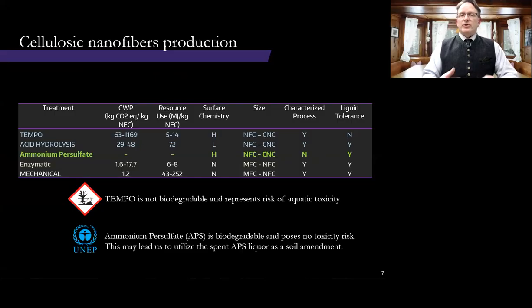With regards to the way we produce nanofibers, there are three methods for producing nanofibers: chemical, enzymatic, and through mechanical means. This table summarizes the environmental impact, the energy requirements, and then what that process is capable of developing in nanofibrillated cellulose. But to produce a nanofiber that helps solve our environmental problem, we really need to have an environmentally friendly method. And of all these methods, enzymatic and mechanical methods are the most environmentally attractive. However, mechanical requires the most energy to accomplish. And unfortunately, both are limited to the upper range of nanomaterials, so microfibrillated cellulose and down to the largest size nanofibrillated cellulose. What that means is, in order to get the same physical properties, you have to use more of the fibers compared to nanofibers.